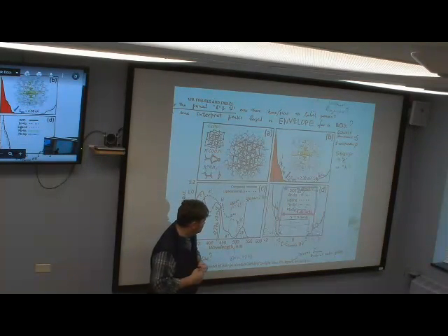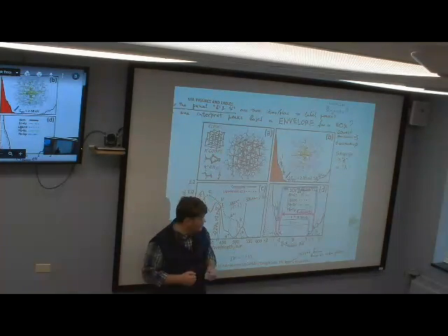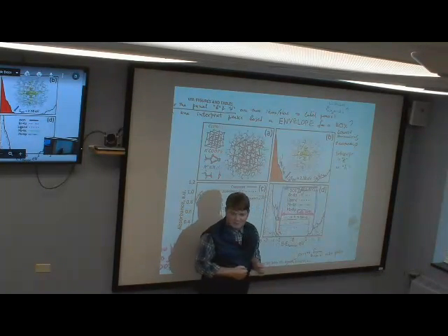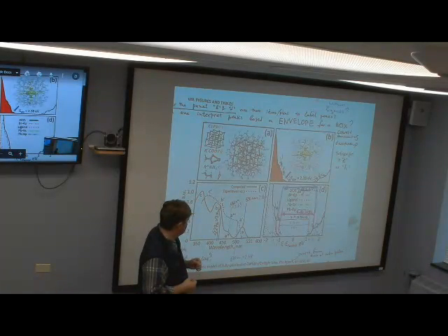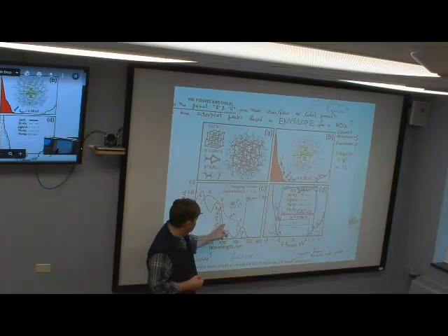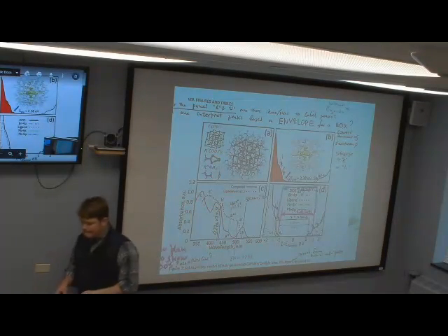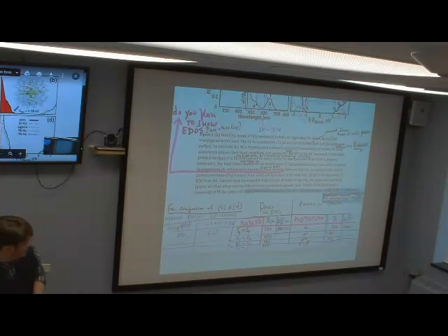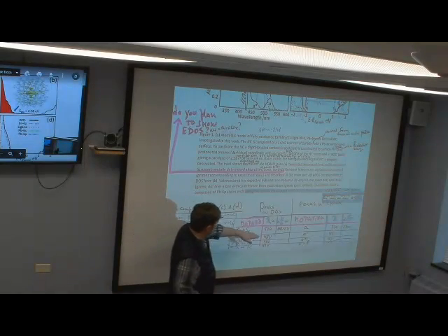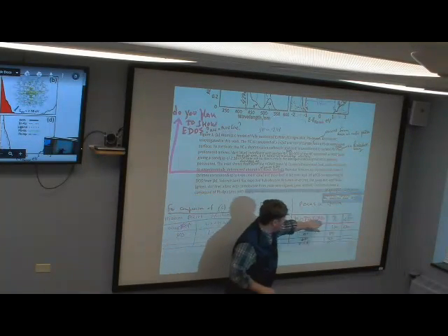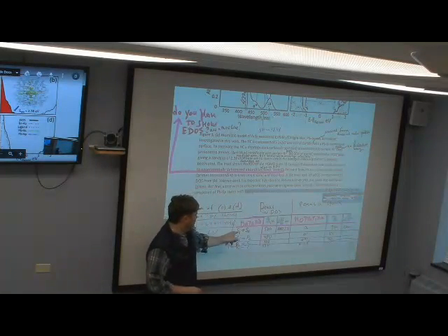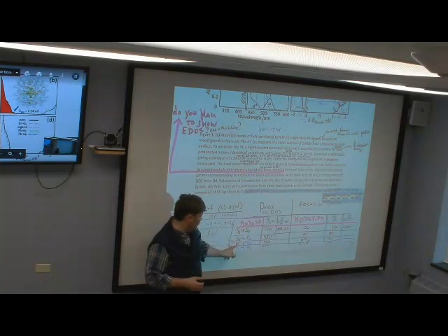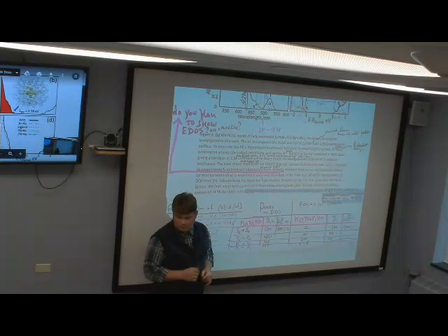I was just sitting and playing with a calculator, trying to subtract these numbers and see which transitions they generate. So the first 4 peaks could be summarized in the same way, as you can put a table for peaks in density of states and peaks in spectra, and those could be S to S, the lowest one, S to P, P to S, and then P to P. And it works really well if one looks through the numbers.